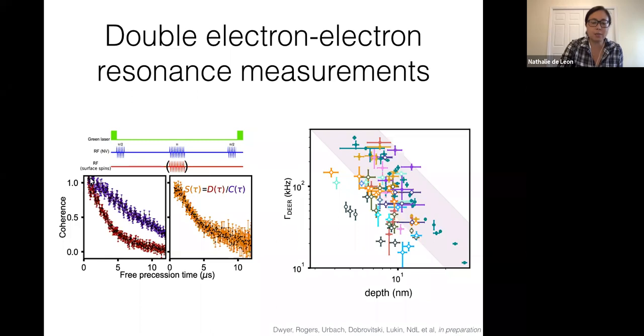So the way that these experiments look is, this purple trace here is a Hahn echo decay curve of a single NV center. And then when we add in the second pi pulse, we get a faster decay in this red trace here. And then if we just divide these two curves, we get out a signal that is the decoherence due to these surface spins. And it's essentially like a free induction decay measurement on the NV center. So we had done these experiments for a very long time and had a very large data set from our lab over the last several years.